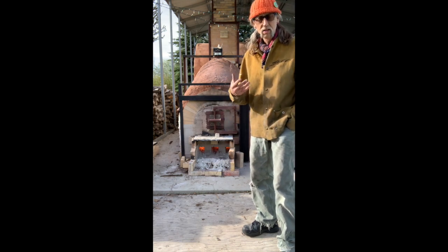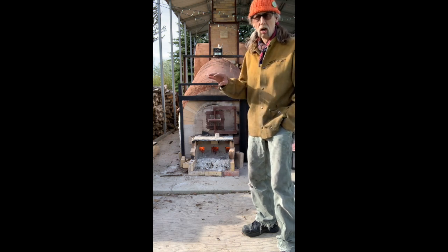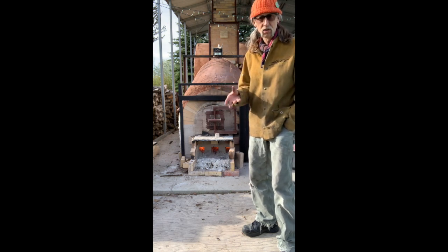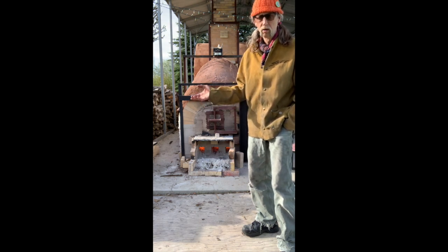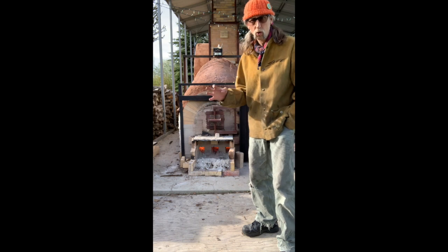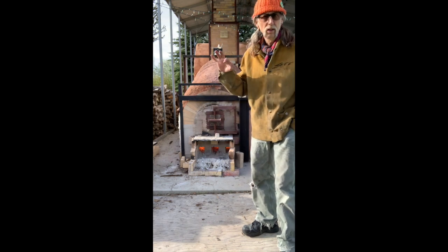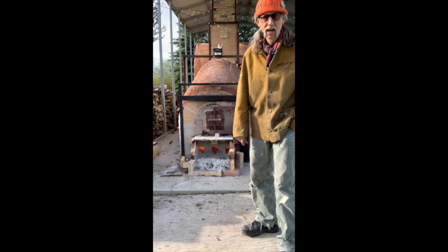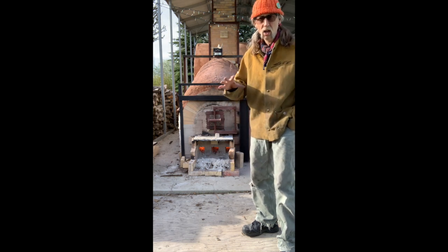But the aesthetic that you get from this, compared to a soda kiln, it's atmospheric firing aesthetics. And you can layer and layer different kinds of wood ash. Different types of wood that you're going to use is going to have a little bit of a different effect too. For instance, pine is green, oak is a yellow, golden, willow can be bright yellow, cottonwood's like this gray kind of weird concrete ash, and cottonwood seems to have more sodium in it. I'm not quite sure exactly what's happening.